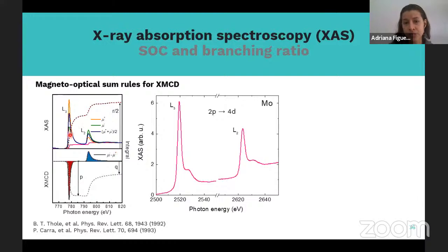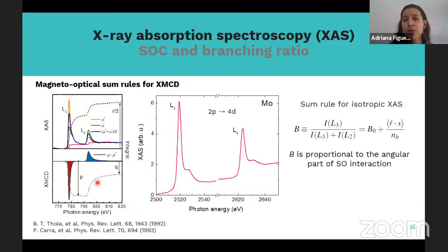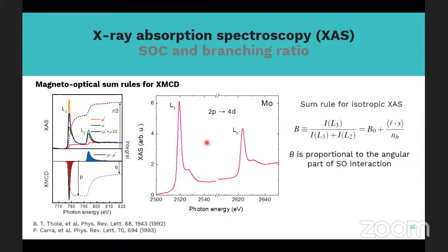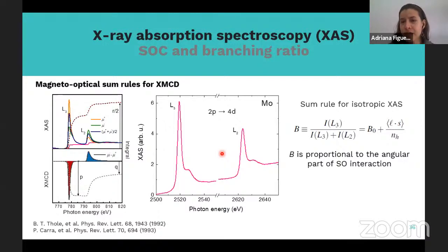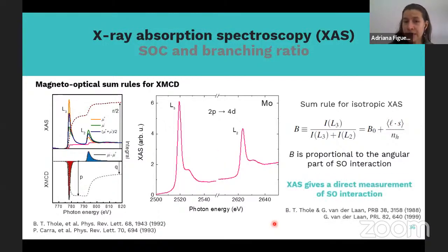without the application of a magnetic field, we find that there is a sum rule for this isotropic XAS that relates the integral of this absorption spectra with the angular part of the spin-orbit interaction in this material. For example, here I'm showing the case of molybdenum, because I'm going to show you results about graphene interfaced with molybdenum disulfide. XAS gives you a direct measurement of that spin-orbit interaction if we analyze those spectra with this sum rule for isotropic XAS.